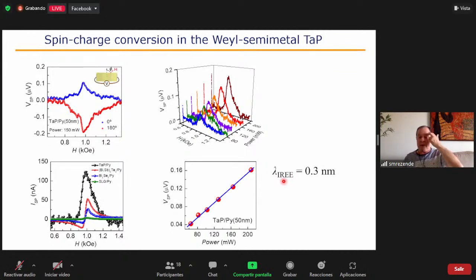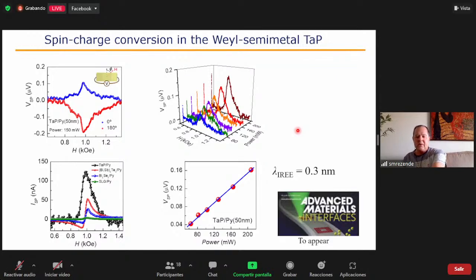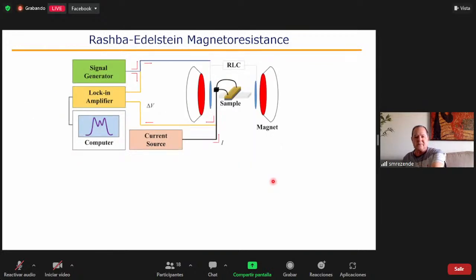and this has a very large Rashba-Edelstein parameter, 0.3 nanometer. This is 100 times larger than graphene. And this has a size that can eventually be used. This is all at room temperature. All I'm showing here are measurements at room temperature. So this is an efficient converter of spin current into charge current. This is almost accepted to be published in Advanced Materials Interfaces.